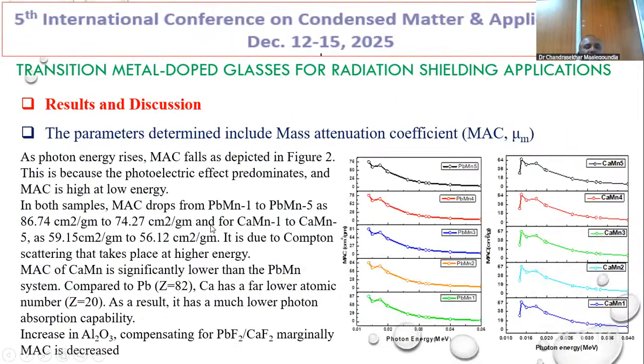These graphs represent mass attenuation coefficients. Here I prepared the PbMn1 to PbMn5 glasses. It is clear from these graphs that as the photon energy increases, the mass attenuation coefficient is decreasing. From sample 1 to 5, it is decreasing. Why is it decreasing? Lead is replaced with aluminum oxide, where lead has a high Z, that is atomic number, and the mass of lead fluoride is much greater than aluminum oxide. So the value decreases from M1 to M5, as aluminum oxide increases and lead decreases,